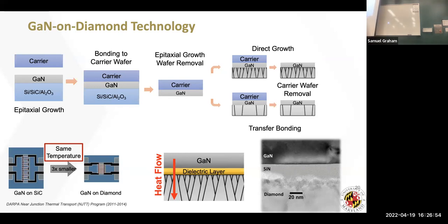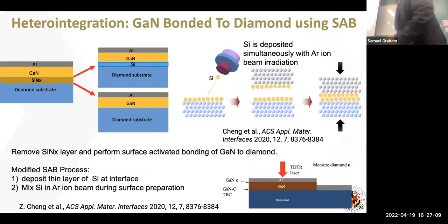So what I showed you here is that I can try to bond. And remember, I'm doing the bonding, and I'm showing you the cartoon that there's nothing at the interface. And so can anyone guess what's going to happen in the real picture? Is there going to be something at the interface? Of course. All right, so here we go. So this is the picture. So what we found is that it's hard to bond GaN directly to diamond.